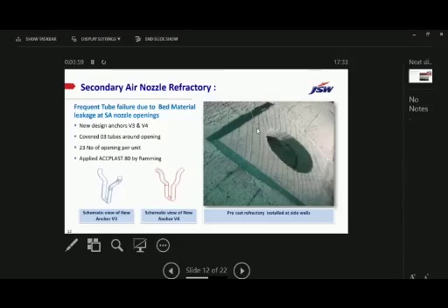These nozzles, due to the high velocity of air passing, suffered erosion around the nozzle area, and it eroded the refractory and exposed the boiler tubes. When a boiler tube is exposed, due to continued heating of hot bed material, it also got eroded, and it will create leakages and lead to unit breakdown.